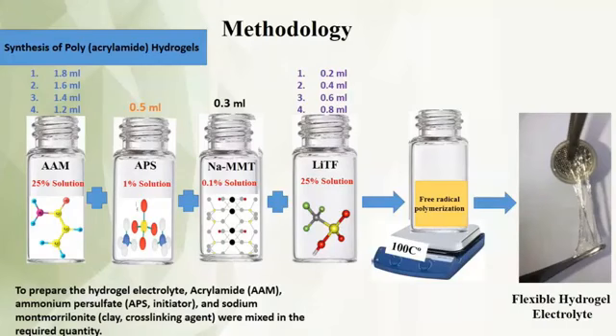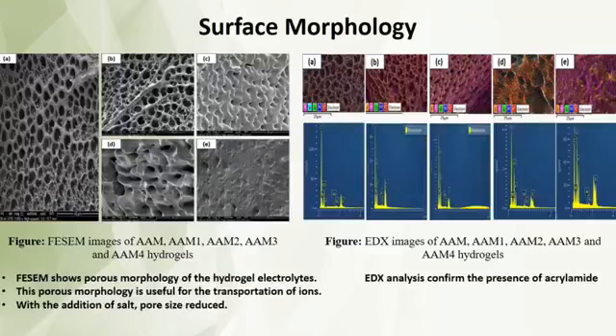Okay, here are some of the results where we use acrylamide as a host material, by using ammonium persulfate as an initiator and clay as a cross-linking agent to prepare the hydrogel electrolytes. Obviously, we need to apply the lithium salt as a source of ionic carriers. So here, the FESEM images show the high porosity of the hydrogel electrolyte. Initially itself, I mentioned that porosity is one of the important parameters we need to have. Then EDX analysis confirmed the presence of the acrylamide.